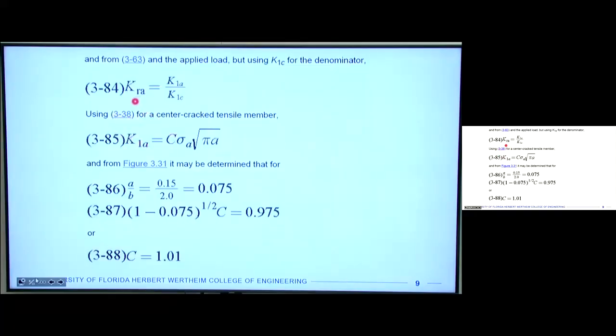Here we're going to calculate the y-axis, which was the normalized fracture strength or fracture toughness. We're going to have our fracture toughness for our problem divided by some normalizing value. To create that chart, they use an effective fracture toughness, K effective, from the strip model. But in this case we have a tensile load, so it's a very simple case, and we're going to use K1C. That's what they use in this book example.